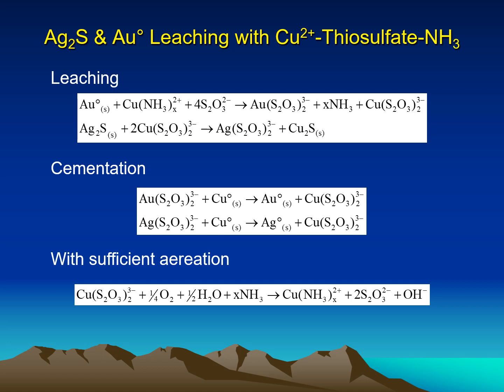And in this case, we'll be leaching the gold by oxidation, and the silver will be an exchange of the copper for the silver to form chalcocite in the solid. So once we have the pregnant leaching solution, it will be cemented with copper metal, and we'll get the gold and the silver metal. And then with sufficient aeration, the cuprous thiosulfate can be oxidized back to cupric ion to be recycled back to the leach.